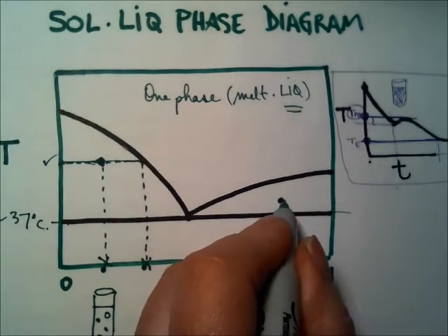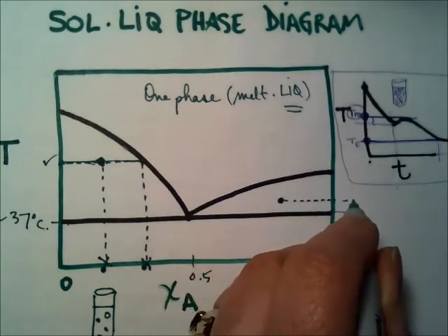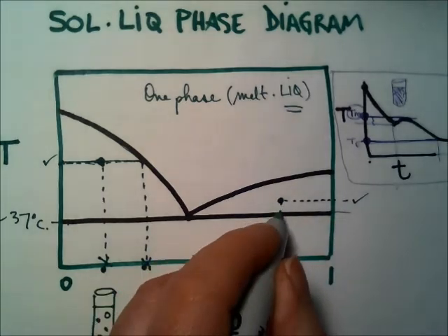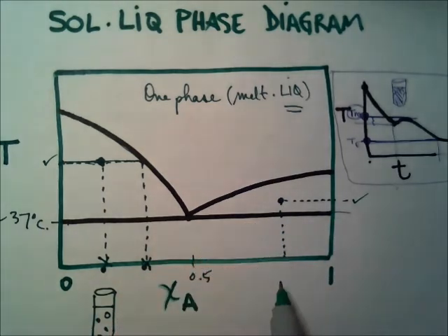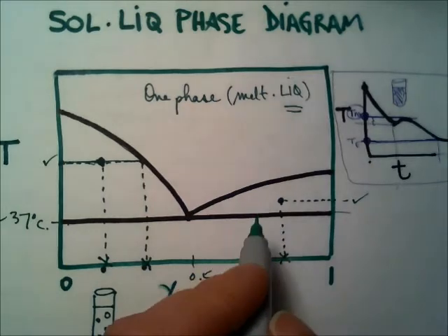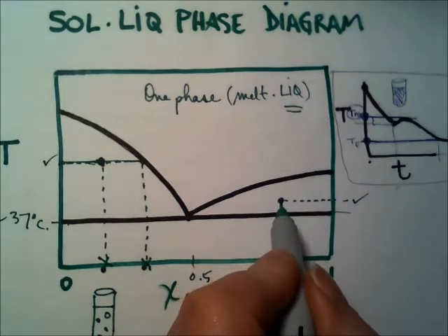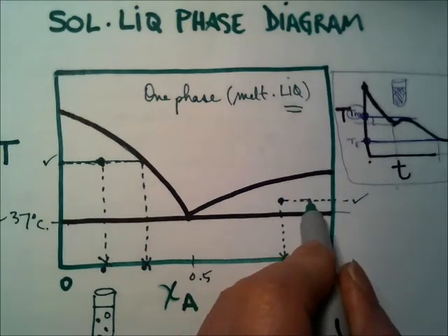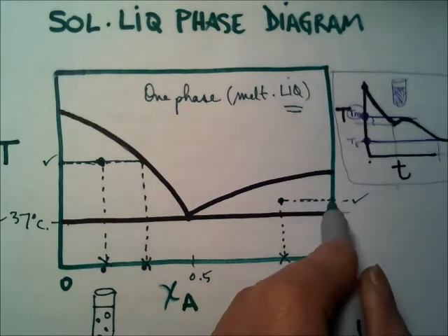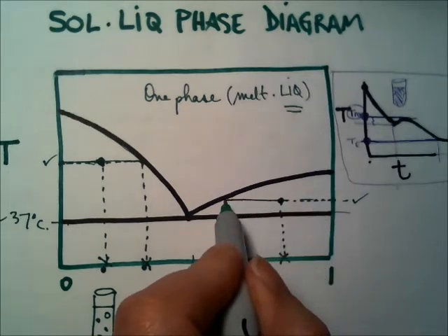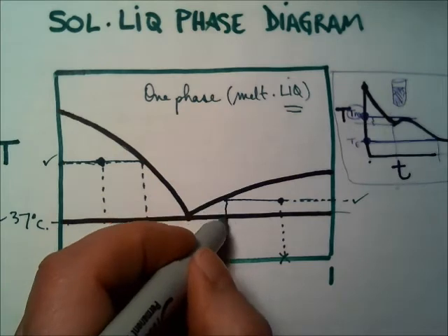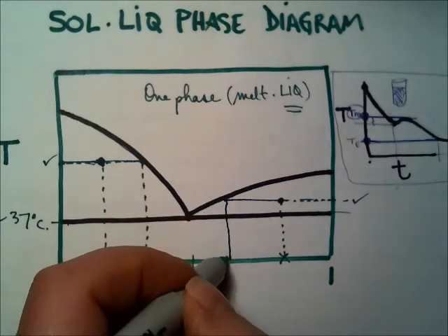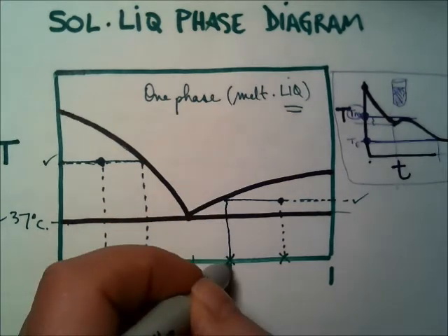Well, the tube is at this temperature. The overall composition in the tube is marked by this mole fraction. Specifically, I have two phases in equilibrium with each other in this test tube. I have solid bits of pure A in equilibrium with a liquid, and the liquid is rich in A but also has some B.